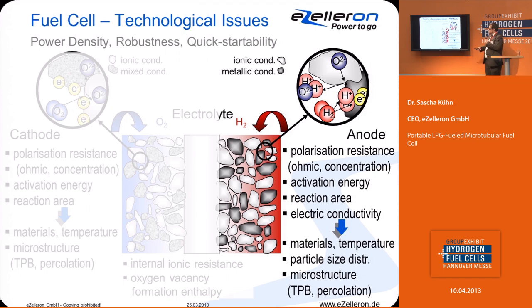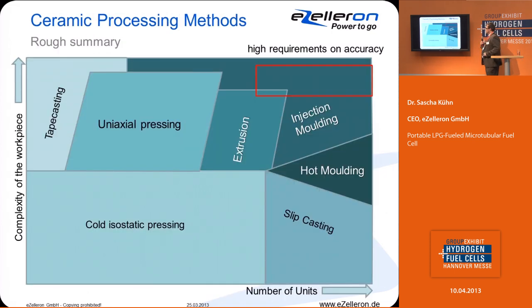Focusing on the anode, it is necessary to look for polarization resistance, and also to lower the activation energy, broaden the reaction area, and improve the electronic conductivity, which means you have to care about materials, temperature, particle size distribution, and the microstructure. So the first thing you have to think about is how can I manufacture such an anode substrate?